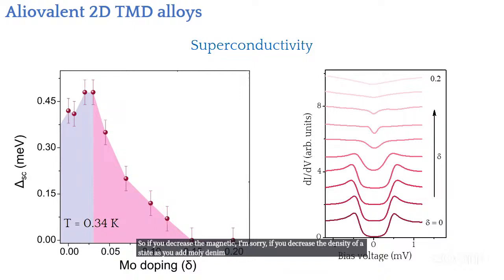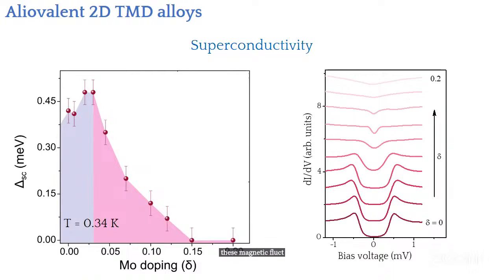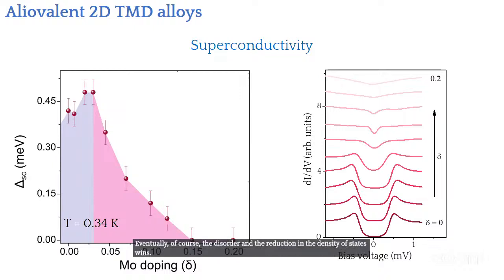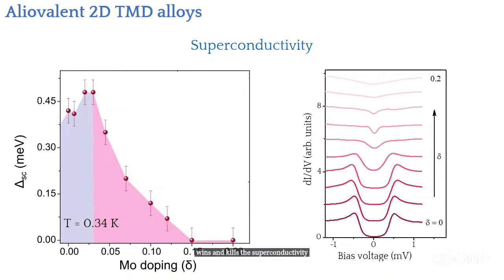So we expect that the magnetic fluctuations are very strong. If you decrease the density of states as you add molybdenum, these magnetic fluctuations, which are pair breaking, are decreased. And that helps the superconductivity to thrive a little bit. Eventually, of course, the disorder and the reduction in the density of states wins and kills the superconductivity, but superconductivity survives up to 15% of molybdenum atoms, which is significant.